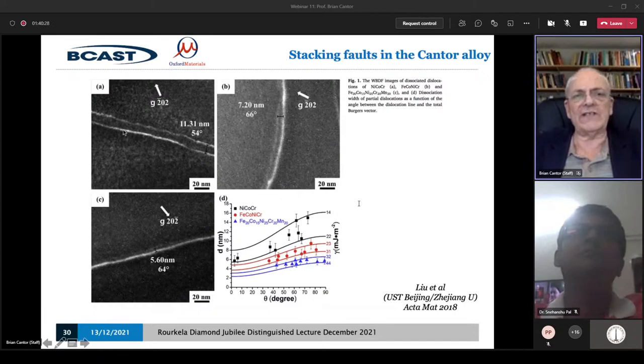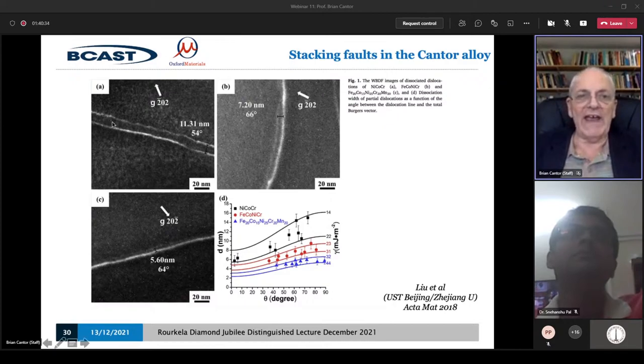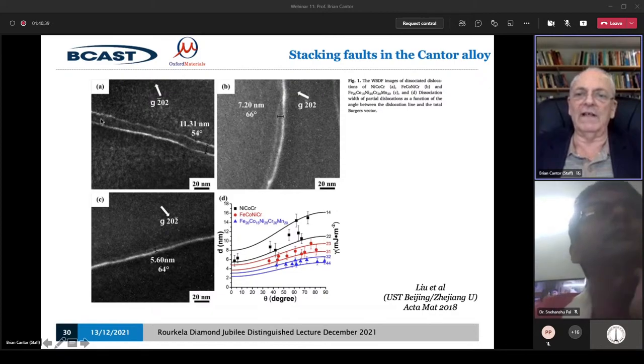Now you're asking me if we can tailor this. We can tailor it, but the most interesting point to notice is that the stacking fault energy varies. The separation of these partials is determined by the size of the stacking fault energy. If the stacking fault energy is low, the partials separate a long way apart. And if the stacking fault energy is high, then they're very close.